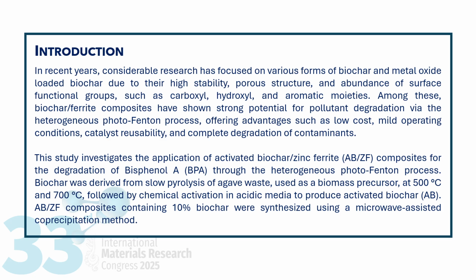This study investigates the application of activated biochar zinc ferrite composites for the degradation of bisphenol A through the heterogeneous Photo-Fenton process. Biochar was derived from slow pyrolysis of agave waste, used as a biomass precursor at different temperatures, followed by chemical activation in acidic media to produce activated biochar. AB/ZF composites containing 10% of biochar were synthesized using a microwave-assisted coprecipitation method.